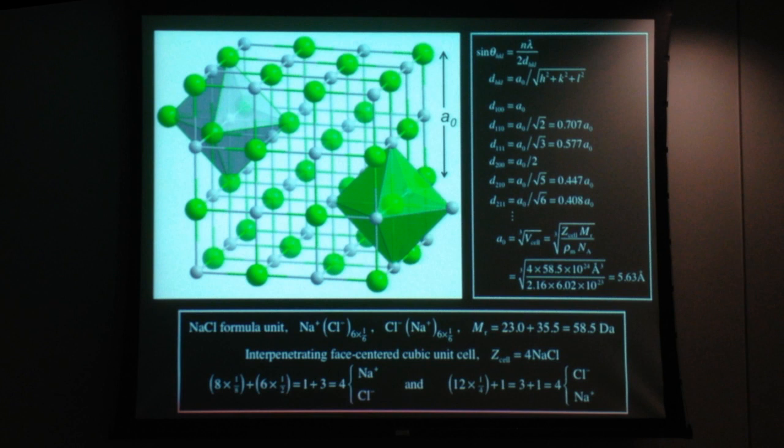The mass density can be measured for these crystals. You can either just take a big one and measure its volume and then weigh it, or weigh a bunch of little ones. In any event, this is a straightforward experimental variable, and the Avogadro number is known. Okay, so that means they knew that a0, the actual length, must be 5.63